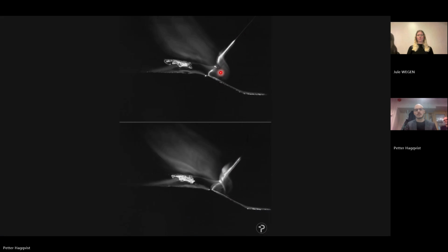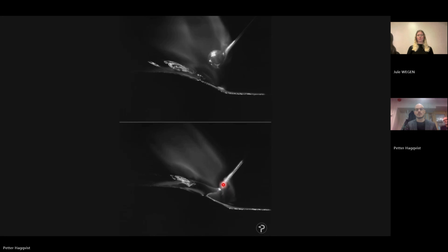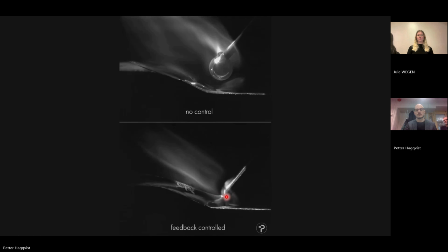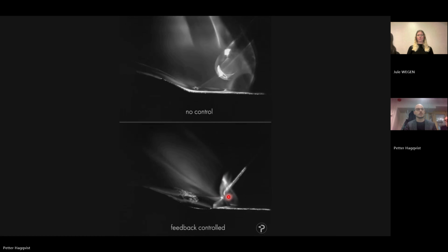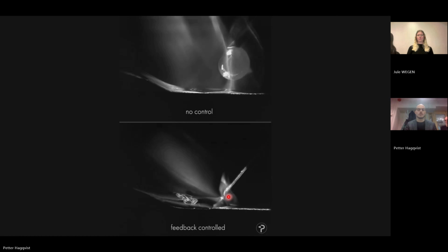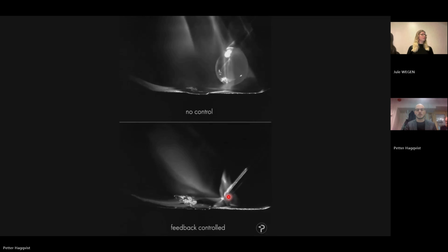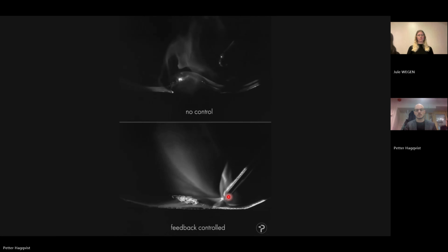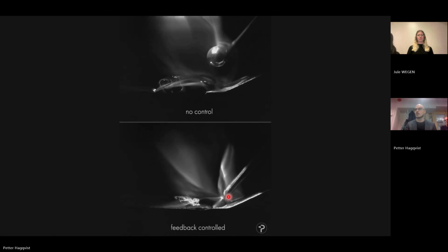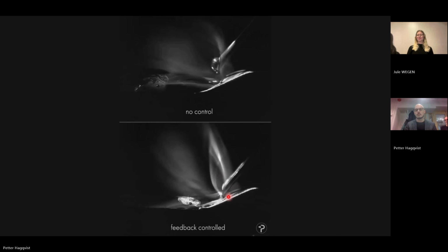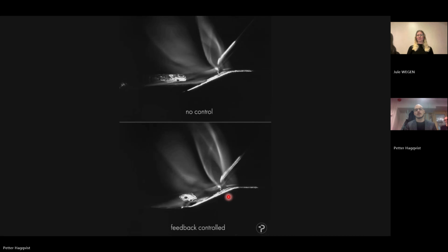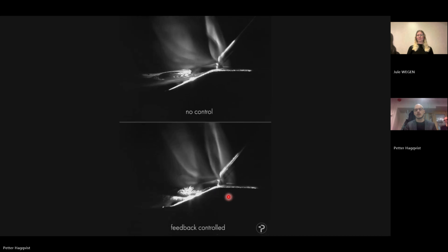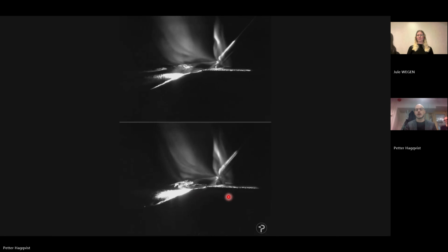And we do this by, when we detect that the wire needs to move downwards like this, that means that we need more material. So within the process window that we've established, which is how much more wire can we add without it getting too cold, we make sure to add that wire. And in the opposite, when the wire is going upwards, that means that we have sufficient material so we could remove or reduce the amount of wire that we introduce to the melt pool.